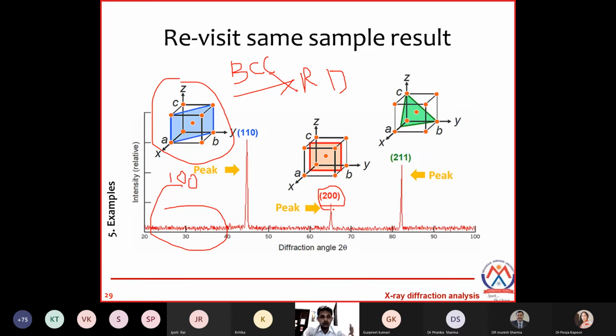Sometimes if there is a systematic absence of the first order, the second order peak is also labeled as 100. This happens a lot of times. It is acceptable. You can write it as a 100 peak also, because it is showing 200. Otherwise it is not a 200 peak, 100 peak, sorry. Similarly, now we understand why we are writing it 100, because we are going to calculate the D distance. So this is D100, D200 and D211. Our theoretical knowledge plus XRD analysis should match, and then only we can interpret results. Although it can interpret bondings also, how bonds are being formed, how bonds are being attached, still that should be on the basis of distance between atoms, distance between planes. That should not be looked into like, because this XRD peak is placed over here, that's why the bond is being formed. That should not be interpreted like that.